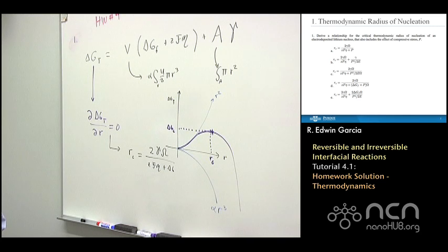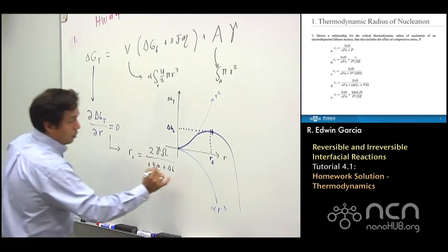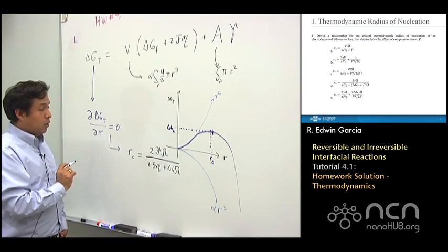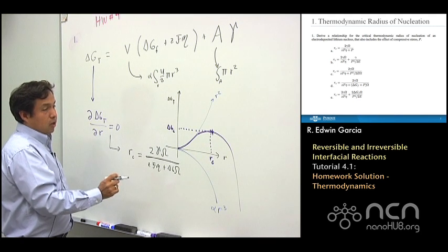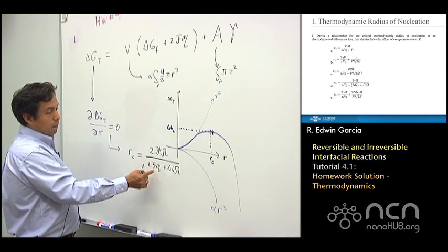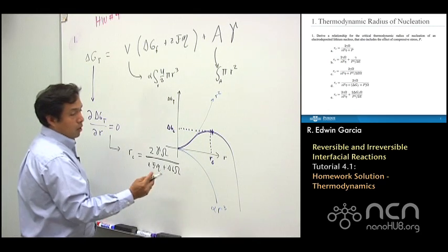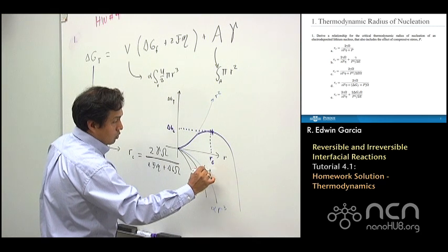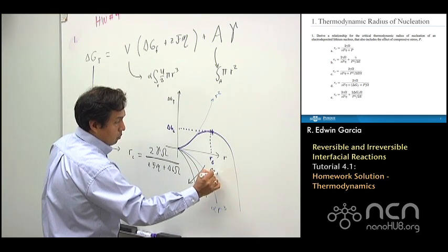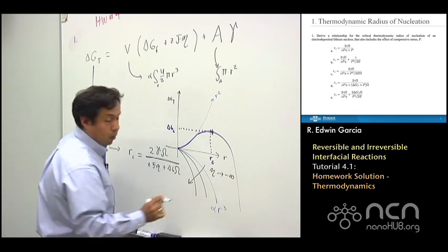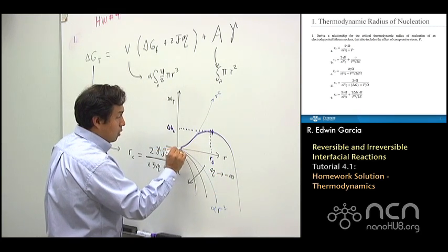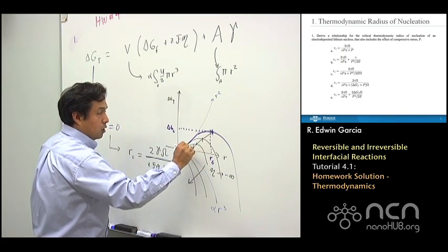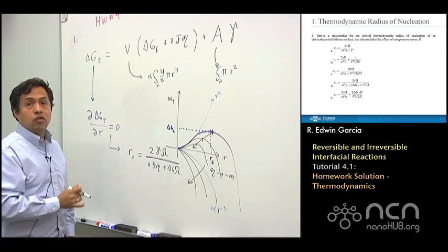This is something we have already done in class. The relationship is such that when we make this overpotential more negative, we make this contribution come further down like this, as eta becomes more negative. When you do that, the energy barrier comes down and the critical radius starts going in that direction. Basically, we favor the nucleation of that phase.